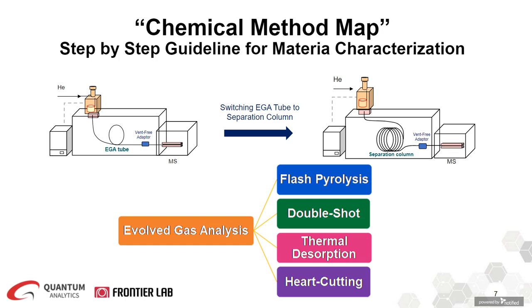As we just learned, you can perform multiple analytical techniques in addition to flash pyrolysis using your microfurnace GC-MS system. Now, to chemically characterize an unknown sample, we have developed a series of techniques referred to as the method map. This chemical method map provides you with 2 simple steps to determining the organic composition of any unknown sample. EGA, evolved gas analysis, is your first step, which provides you with a clear picture of the thermal profile of your sample. The second step is then to use your EGA thermogram to define the thermal zones of interest. So EGA guides you on what to do next. It will show if a thermal desorption, heart-cutting, or flash pyrolysis is needed, or maybe even if a combination of these techniques is required.